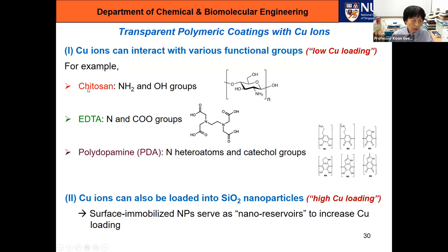So we have chitosan, we have polydopamine, and we have EDTA that we can put on top of the chitosan coating. But the amount of loading of copper ions would be expected to be low because the coating is thin and there's only a limited amount of functional groups for interaction. So we call this the low copper loading surfaces. Then in order to increase the amount of copper loading, we decided to use silica nanoparticles because the silica nanoparticles can act as nano reservoirs for loading our copper ions. So we call this the high copper loading surfaces.